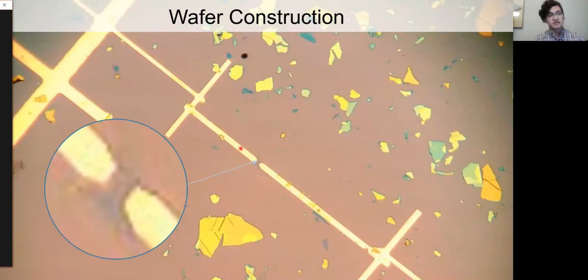Right here, you can see the actual construction of the gold. The gold is deposited. Now the gold electrodes have been set, and the graphene has been positioned right with the gold electrodes. Now, to make sure that there's no leakage, that the graphene perfectly seals the membrane and the micropore is completely covered and our electrodes are properly connected, we have to actually now assemble our wafer.